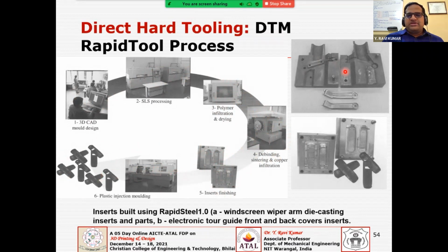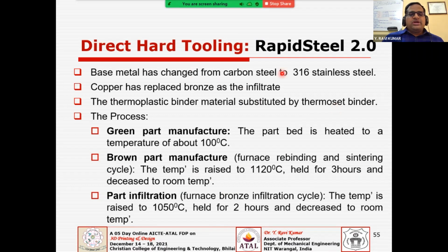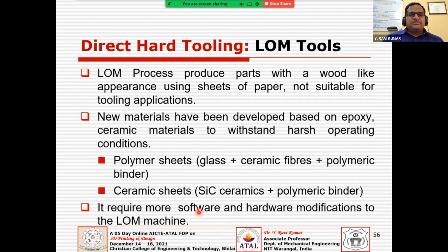And you have other dies, and the parts have been produced. Dies and parts have been produced with rapid steel 1 and 2. There is a slight difference. You have different temperatures and different infiltrants you are going to use here, but it has the green part, brown part, and then followed by infiltration, 2 hours at room temperature, and the temperature raised to 1050 degrees C. And this is the furnace treatment that should be done.